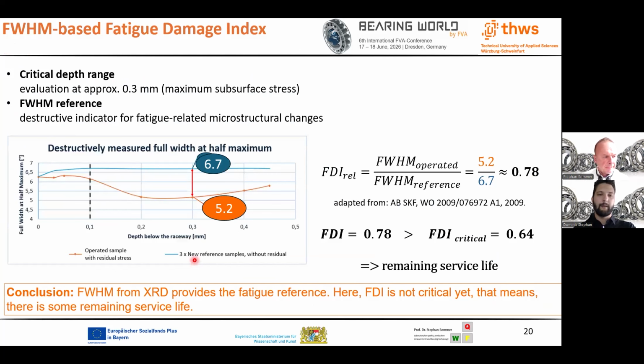Here, we use the FWHM value to calculate the relative fatigue damage index. The evaluation is performed at 0.3 mm below the raceway. This is the critical depth range because it is close to the maximum subsurface stress and because both ECT and FWHM show clear changes there.